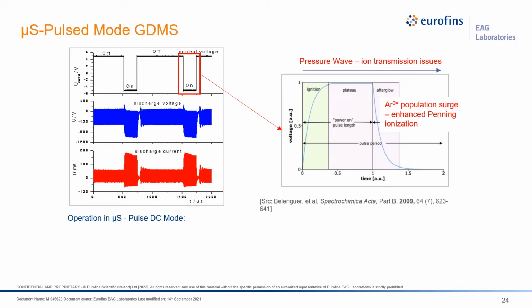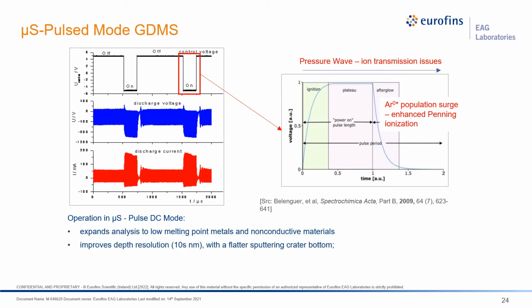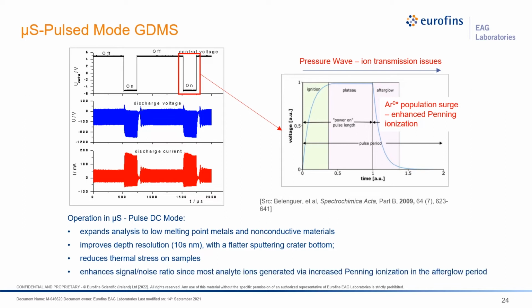Overall, operation in microsecond pulsed DC mode can expand the analysis to low melting point metals and non-conductive materials. It improves depth resolution to tens of nanometers with a flatter sputtering crater bottom. It reduces thermal stress on the sample. It enhances the signal-to-noise ratio, since most analyzed ions are generated by increased Penning ionization in the afterglow period.